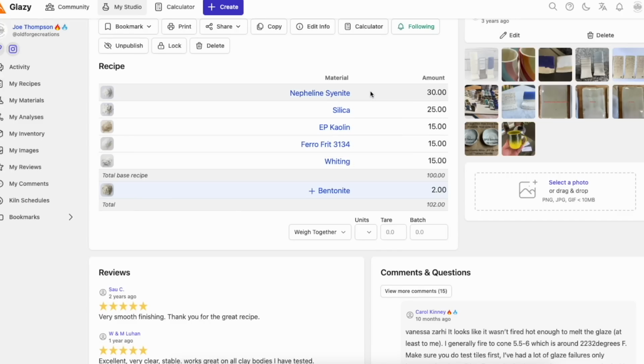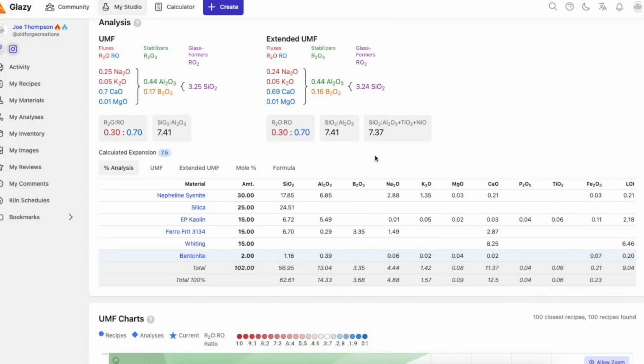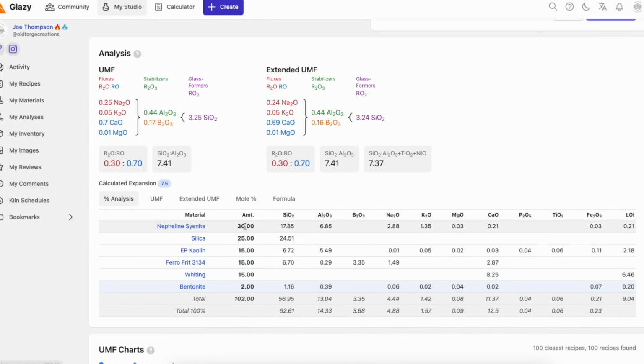You can get a rough idea if you know what each thing has in it, but even then it's quite tricky, which is where we've got this amazing tool called Unity Molecular Formula, or UMF, which does exactly that. So what we've got here is each ingredient, then the amount of silica, alumina, boron, sodium, potassium, magnesium, calcium that it provides. So each ingredient will provide some of these categories. And as I said, you can see silica is actually just a pure silica source. Kaolin provides some alumina, but also some silica and then trace amounts of other things. Whiting is just a calcium source. The frit, while it does bring in the boron, which nothing else brings in, it also has silica and alumina and some of each type of flux.